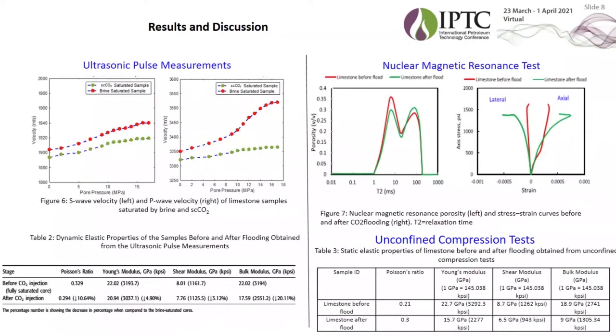Figure 6 shows changes in the primary and shear wave velocity during brine and supercritical CO2 flooding. As can be seen in the figure, the brine saturated sample gives a higher primary wave velocity compared to the velocity when the sample is saturated by CO2. However, the trend of shear wave velocity in the brine saturated and supercritical CO2 saturated samples are similar but less than the P waves.